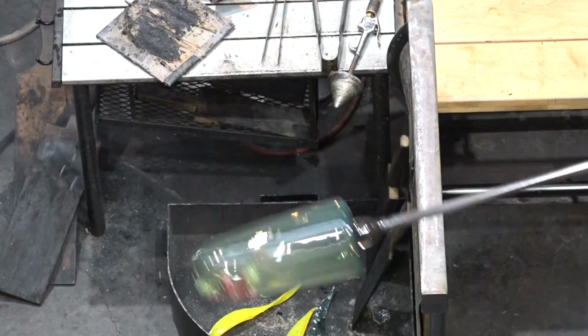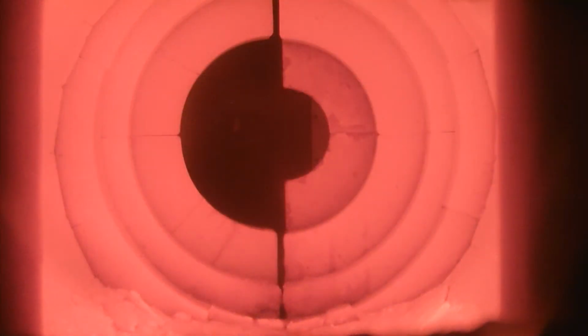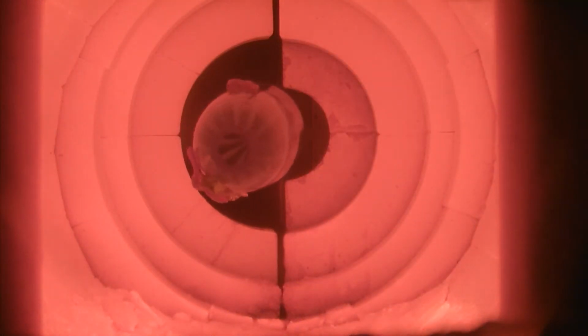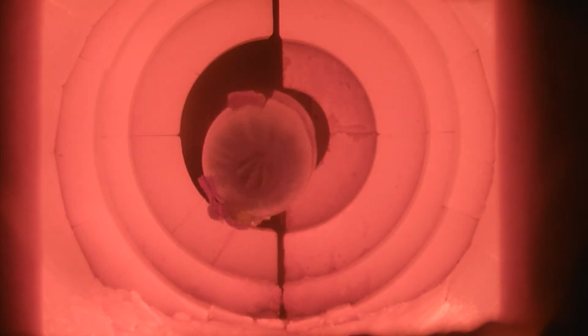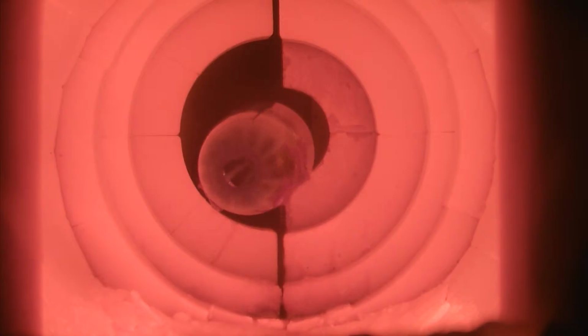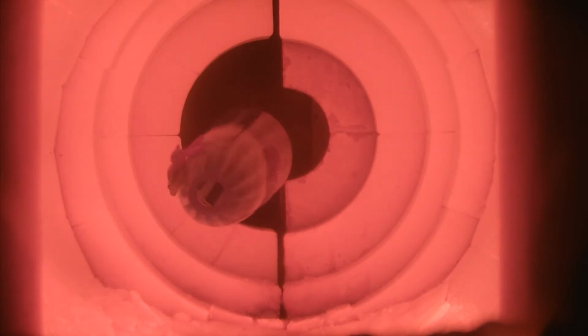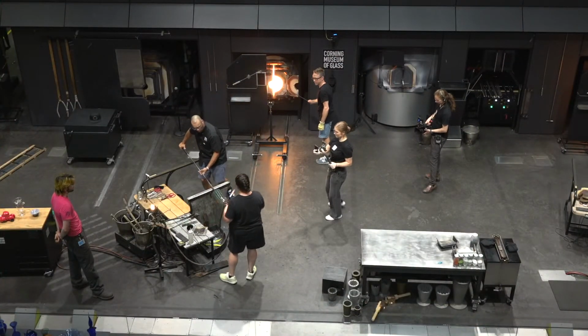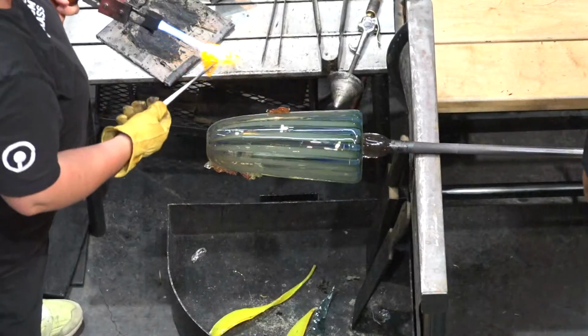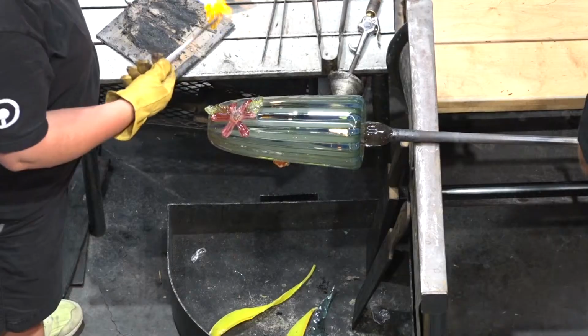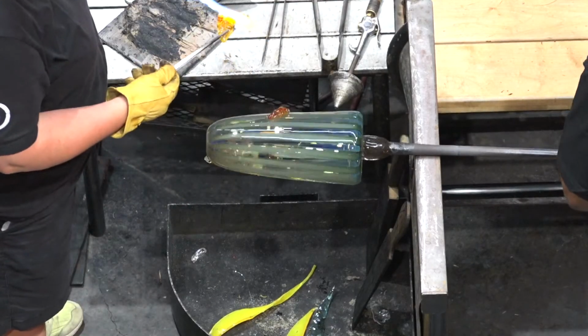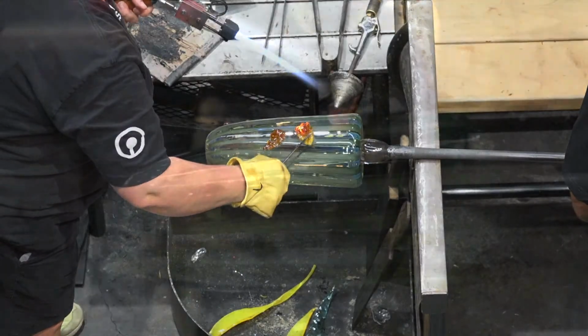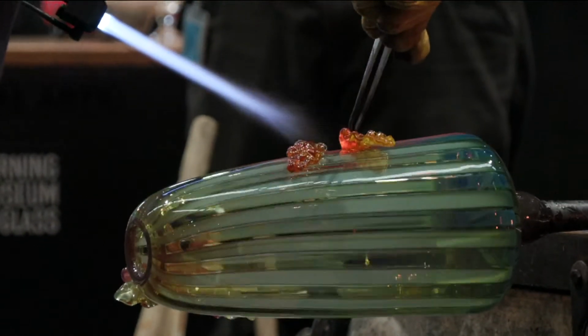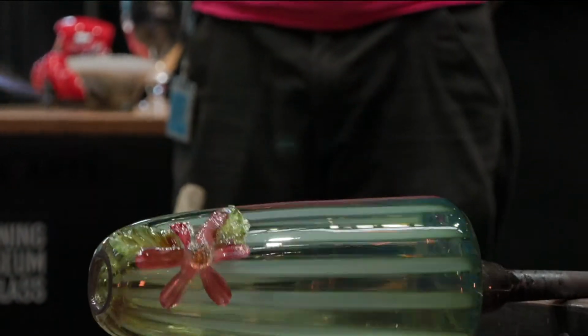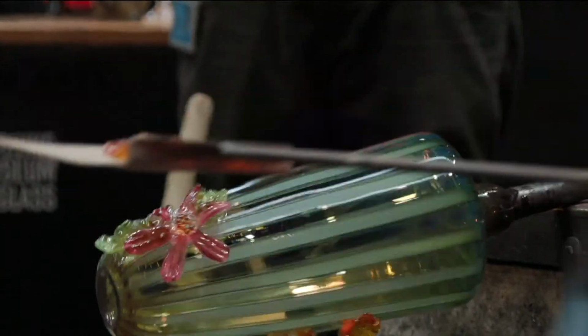And we have a larger piece, which is more fragile. So we want it to be brought up slowly. So what we do is we put it into the glory hole. The glory hole, we can heat up slowly. And this side of the garage over here is around maybe 1,050 degrees. And then this side over here is maybe around 950 degrees. So what we can do is put the glass in here, bring it over to this really hot part, and then go from 1,050 degrees right into 2,000 degrees. The jump from 900 to 2,000 is too high, but from 1,050 to 2,000 is pretty safe. So that's what we do.